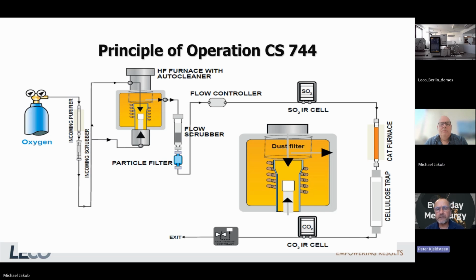And then the other is, when you reach these temperatures, you're not producing CO2. You make a lot of carbon monoxide. Yeah, keep in mind. Theoretically, if you look at the Boudouard equation, yes, but practically, more or less not really, because we're running a huge oxygen surplus in the system. We have really a lot of oxygen. It's running under pure oxygen. Okay. But the question is good.